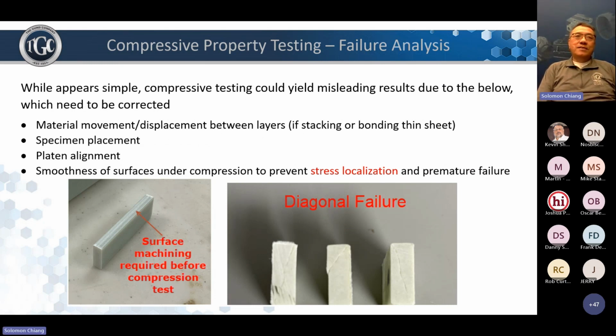Okay, so even though it looks simple, both ASTM and ISO methods require that you make sure the coupons are properly aligned. A good UTM is self-aligning. If the alignment is off, especially with tensile, you get bad results. And for compressive tests, you have to make sure that the surface facing the platen is perfectly flat.